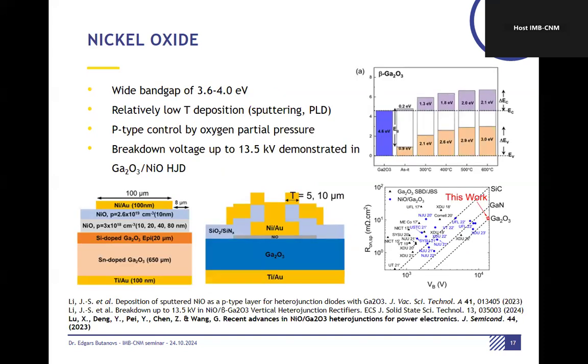I will briefly mention also a material such as nickel oxide. It's a wide band gap material, with a band gap around 3.6 to 4 eV, and it's a p-type material. As people have shown in the last, let's say, 3 years, it has first of all a nice band alignment with gallium oxide. What is good from a technological perspective, you can get decent p-type mobility at low deposition temperatures. Sometimes you can work at 200 or 300 degrees, so it's relatively cheaper. You can do it with sputtering or pulsed laser deposition. And it's natively p-type, so by tuning oxygen defects, the oxygen partial pressure during the deposition, you can optimize this p-type conductivity.